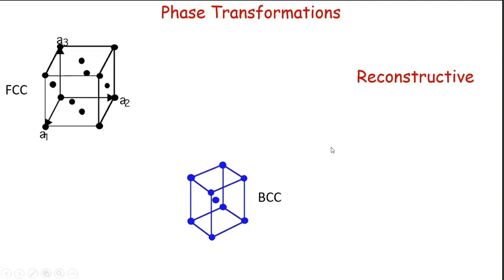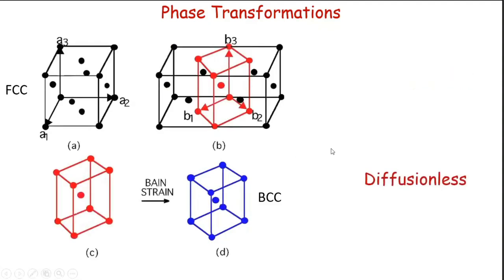And the alternate would be the diffusionless transformation. See, that involved diffusion because you have to take all this material and diffuse through the lattice and go to the site where you have to construct it all over again, of course, a different structure altogether. But if you look at this, what is otherwise called the Bain correspondence, very famously, is that if you take two austenite lattices close to each other, you can see a cell, which is the BCT, a body centered tetragonal cell, which is already very close to the BCC.